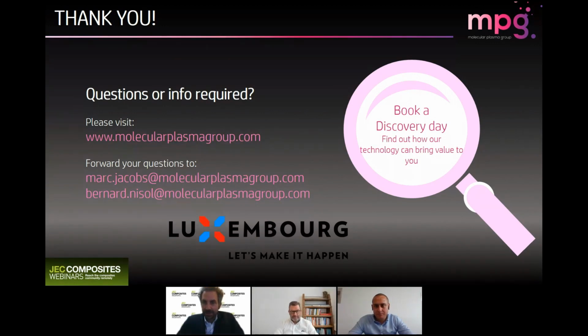Thank you. Next question. Can you treat the ID of glass capillaries with small ID, say 0.3 millimeter over a length of 30 millimeters? Bernard? Yes. So the answer is yes, we can. We are in a range where it's possible for the plasma and the chemistry to penetrate the material very efficiently, and we have been working on such topics, or very closely related topics, and we've seen that we can indeed treat the inner walls of capillaries or whatever other material that is shaped like that. The problem is more from the engineering perspective. So scientifically it is possible, but how to make it work is not necessarily straightforward. I'm not saying it's impossible, but there's a little work to be done up front. Right, Mark? Yeah.